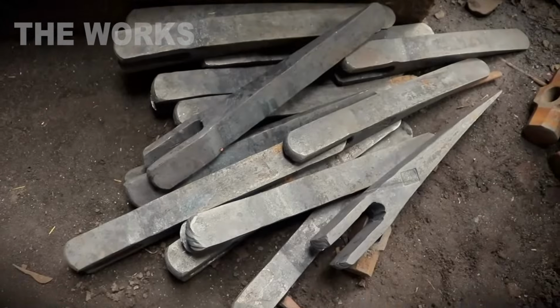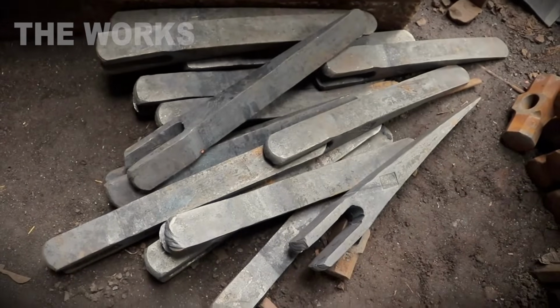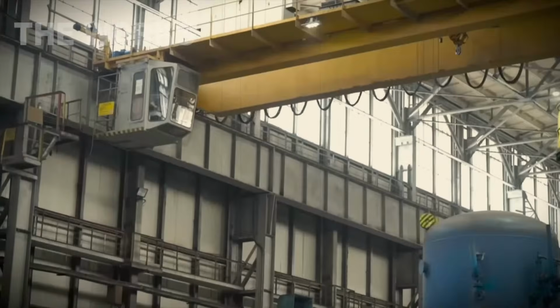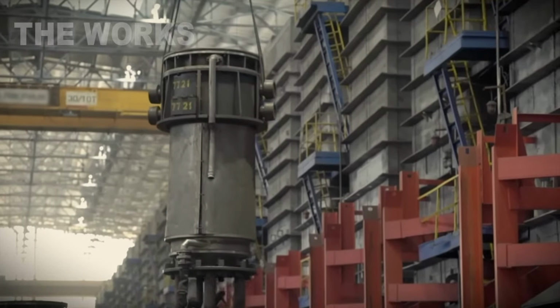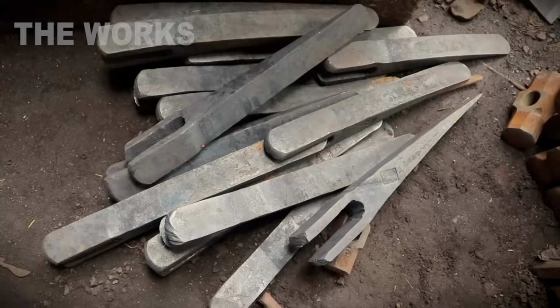Wear test. The tooth gets abraded. Quartz sand with 500 micrometer grain size. 5-bar pressure. 100 hours. That's equivalent to 1,000 hours of operation. The best teeth lose less than 0.5% of their weight.